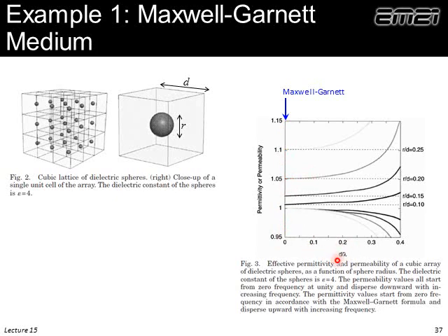So let's think about what this is. When d is 0, that means our unit cell is very, very short relative to the wavelength, and that's a requirement of the Maxwell-Garnett. This is really sub-wavelength. So the parameter retrieval is working. It's only when the periodicity starts approaching and looking photonic crystal-like that it starts to deviate.